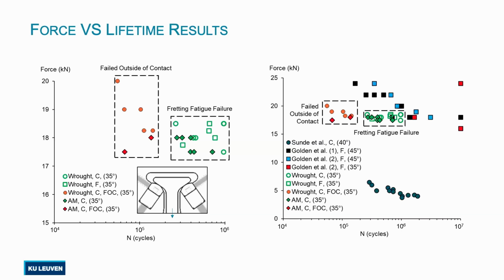But for AM material, we found already the proper loading condition, which should not cause any extra stresses, but we had at least 2 or 3 failed outside of the contact. So it failed not here, but here. I'll dig into it later.